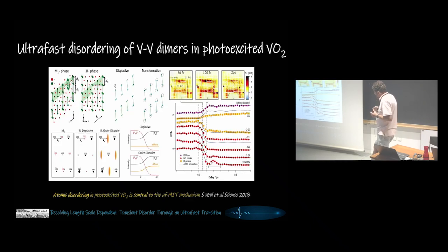Okay. And then to characterize disorder in this type of systems, it has recently been reported, the ultrafast disordering of vanadium dimers in another famous system, vanadium dioxide. It turns out this was a study done on a single crystal, where you have to focus on diffuse scattering features upon application of your pump. What they were specifically looking for is whether the nature of this transition is displacive, in which case the diffuse channel is inert, or order-disorder, in which case, apart from Bragg pattern switching, you also have a diffuse signal that pops up. And that's what they saw.